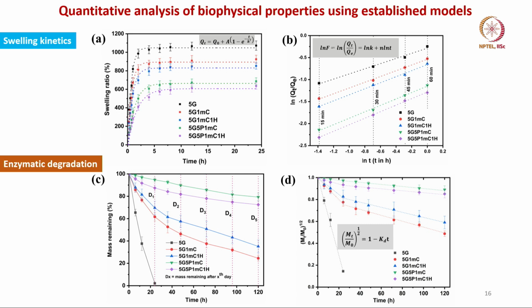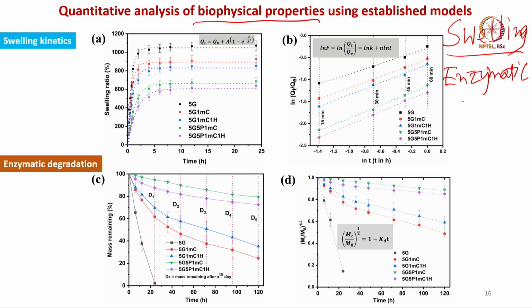Now, regarding biophysical properties, there are two that are very regularly analyzed in the hydrogel community. One is the swelling properties, and the other is enzymatic biodegradation, which people typically evaluate in collagenase solution. First is the swelling. Swelling is typically measured for up to around 24 hours. At different time points the swelling ratio is calculated, and swelling kinetics can be analyzed by this specific equation, where ln of the ratio Qt by Q infinity is equal to ln k plus n ln t, right.